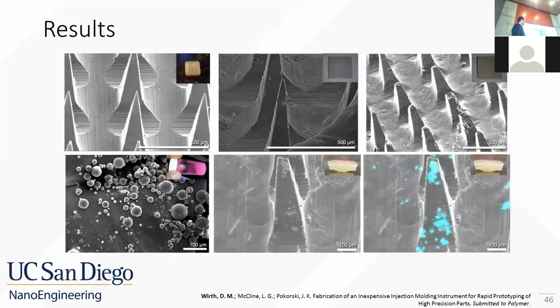Using this epoxy casting procedure, we can make fairly high-fidelity reproductions of these sharp microneedle devices in dissolving polymers. Here's the control sample - this is the positive microneedle mold cast in EMA. We can make a negative of that into a high-temperature epoxy and then injection mold that with polycaprolactone.